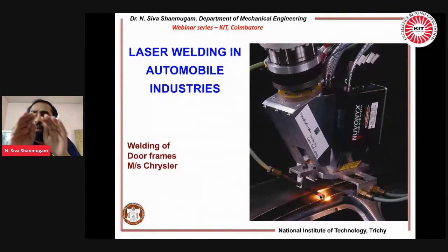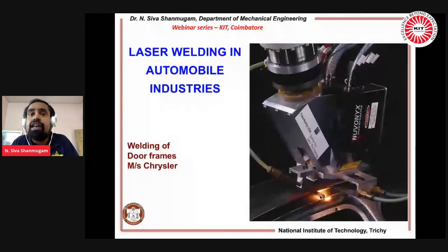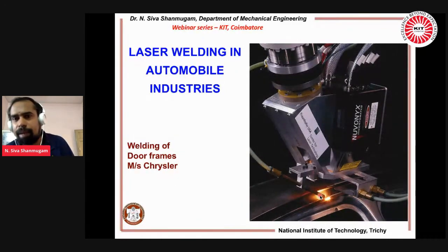Second, it protects the molten pool, because the molten pool is in the liquid stage and has an affinity to mix with the atmosphere. When it mixes with the atmosphere, oxide formation occurs. You get inclusions, and entrapment of oxygen leads to porosity. So to avoid welding defects and also to remove the plasma, we are using the shielding arrangement.